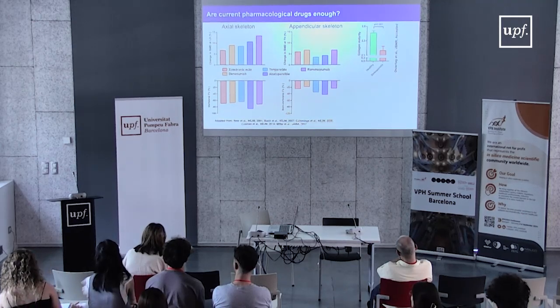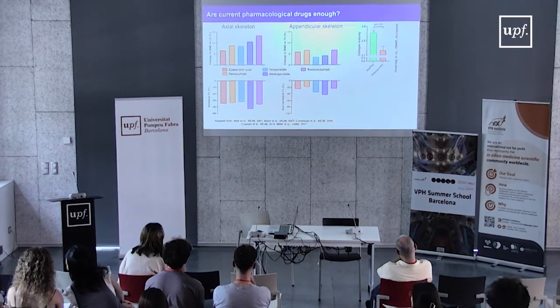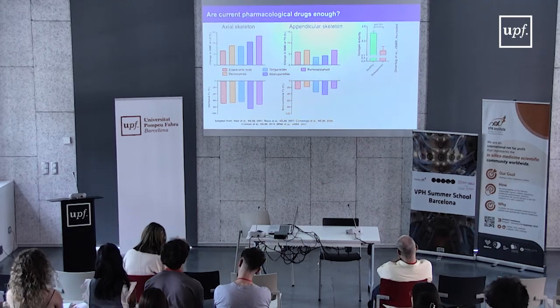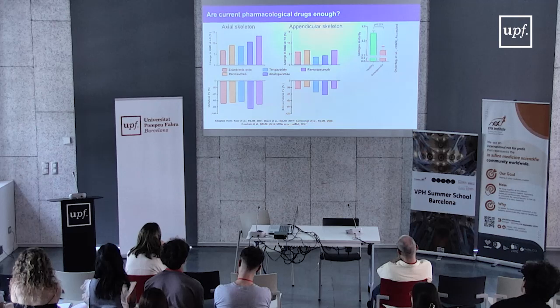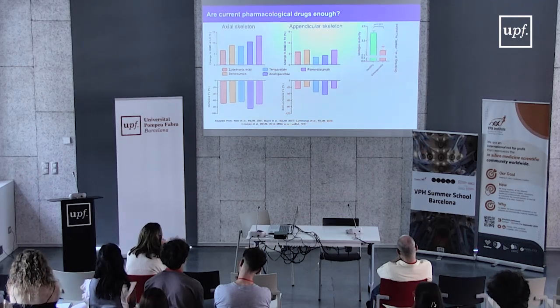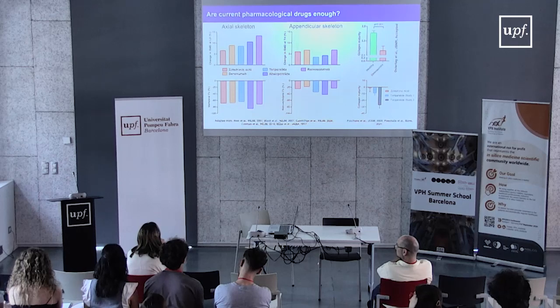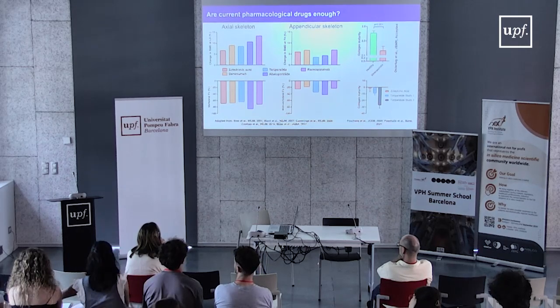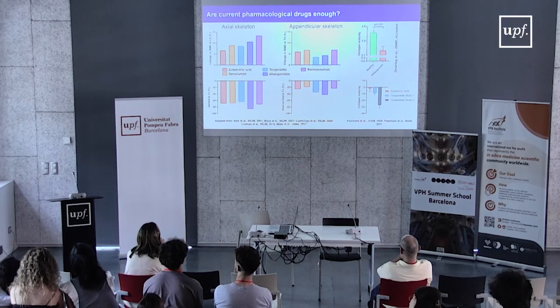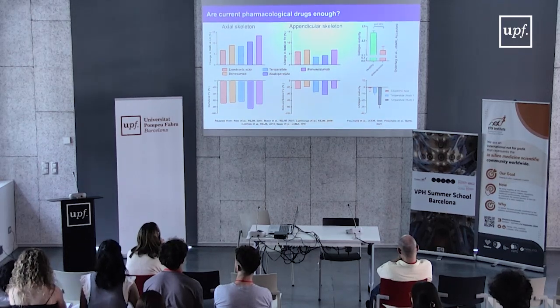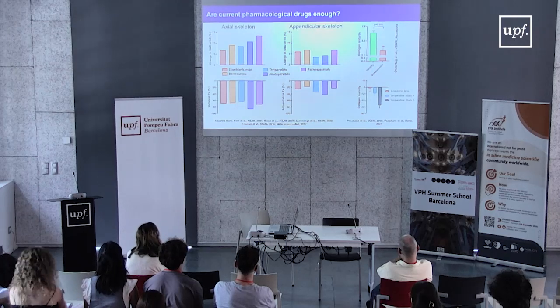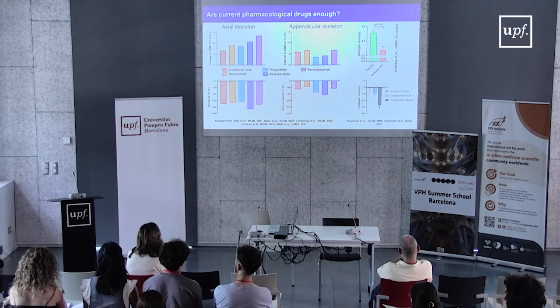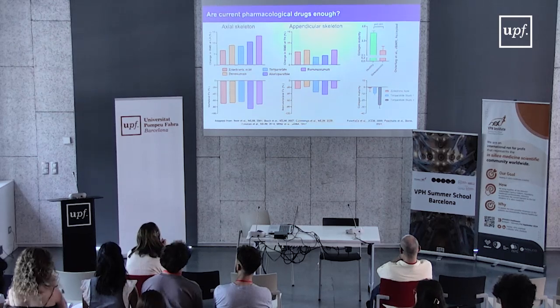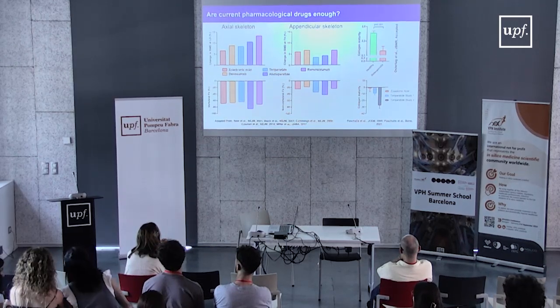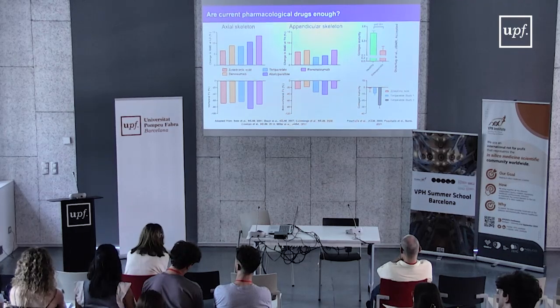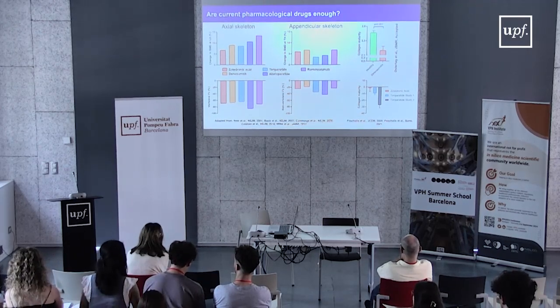We said earlier on that bone material properties are important to have bone strength, and osteoporotic patients especially have lower bone material properties, especially collagen cross-linking. And the problem is that all these drugs, bisphosphonate or anabolic drugs, will reduce even further the quality of the bone matrix. And you can see in here, on the low amount of data that we have in the literature, which have been made through bone biopsies, that bisphosphonates are quite neutral on the cross-linking of the collagen matrix. So despite a small effect on bone mineral density, you have no effect on bone material properties, and hence you are still not capable of restoring a normal bone material property.